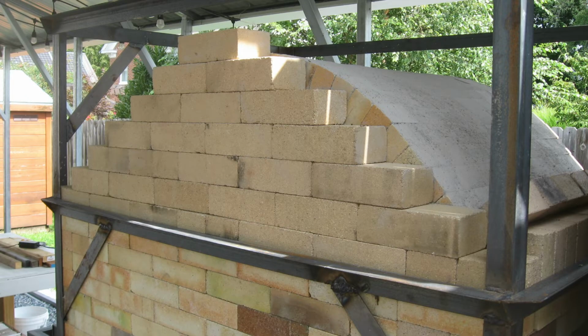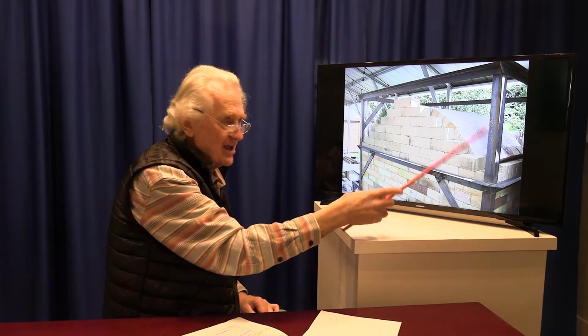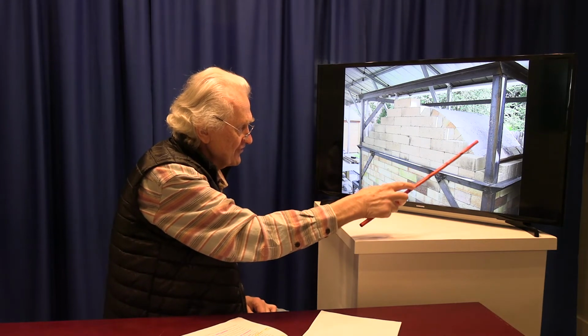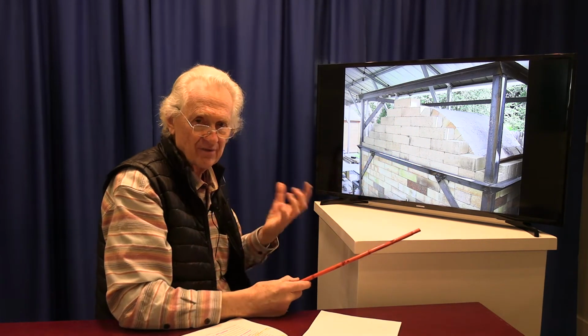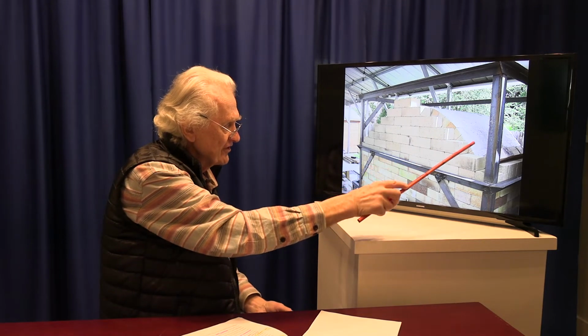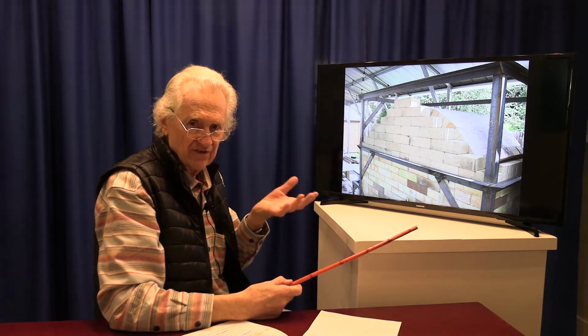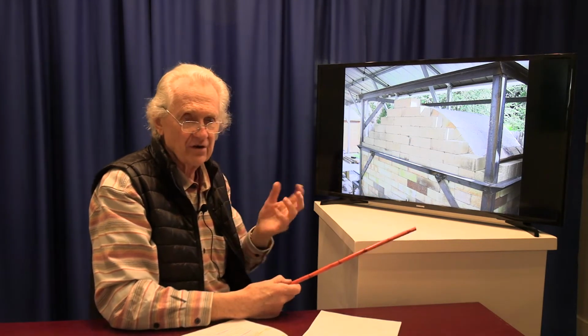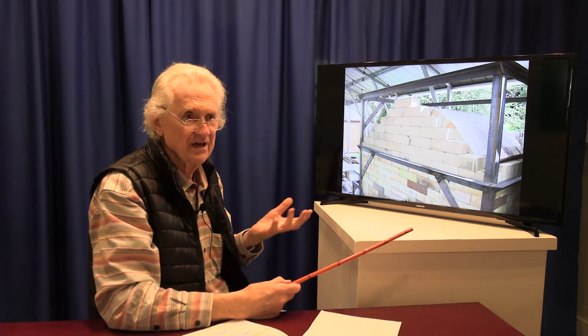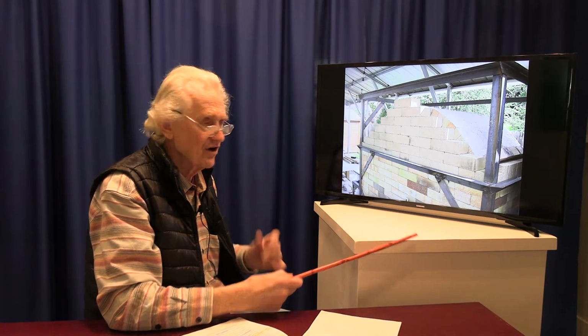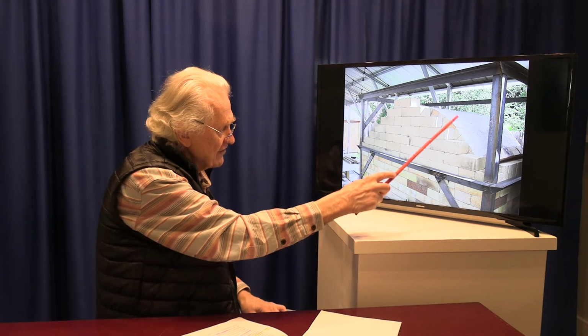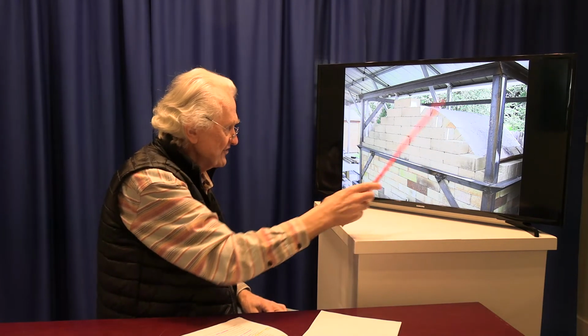And I think we have another view, yep, and there's the final view showing the right-hand side of the kiln with the outside side wall completed. We've actually used the same slip to cover the surface of the arch because we had some extra slip left over. And even though the bricks at this point were all sitting very nicely, because this is going to be a soda kiln and there are going to be vapors coming out, we thought it'd be a good idea to seal the arch. So we just covered the surface of the arch with that same slip.